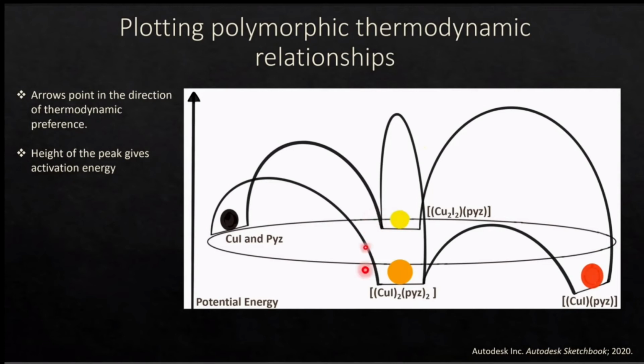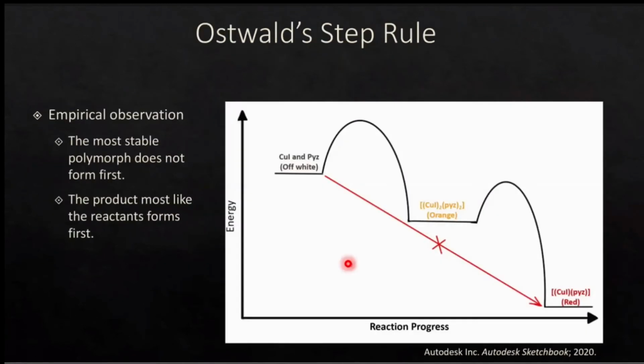Now, this is important because this orange compound is very hard to crystallize. And so we really wanted to be able to verify this relationship, so that way we could say officially that we were making the orange compound in our research. And so this relationship actually follows what's known as the Ostwald step rule, which is an empirical observation. It says that the most stable polymorph is not the one that forms first, but rather the product that is most like the reactants is the one that forms first.